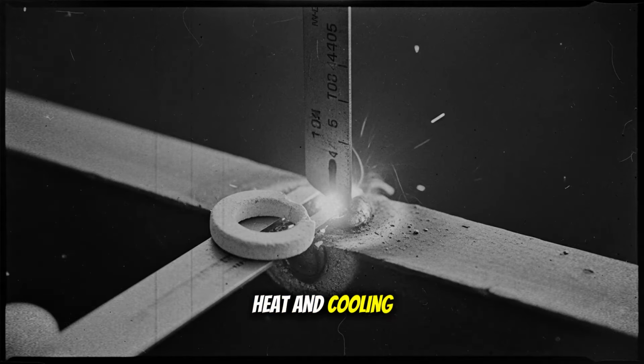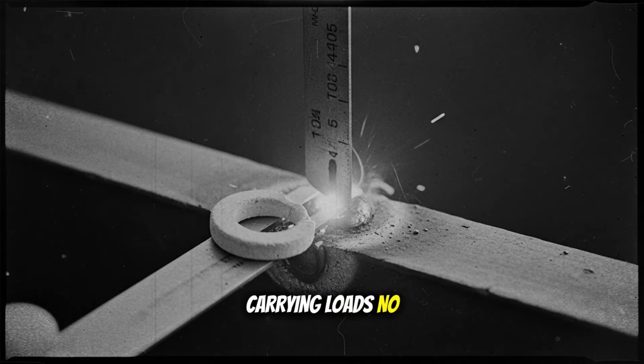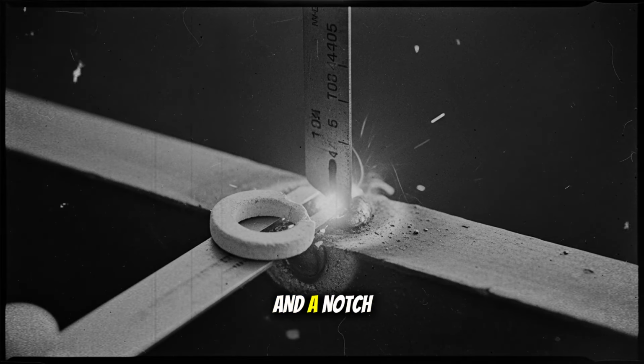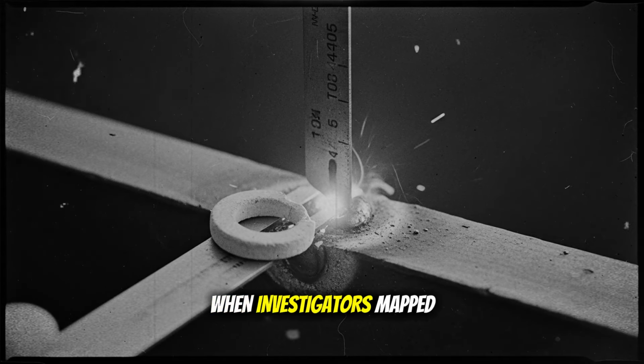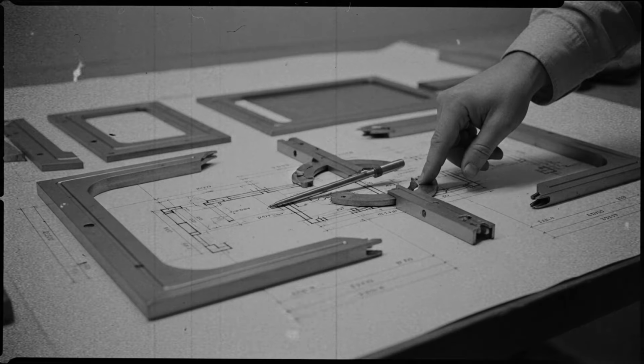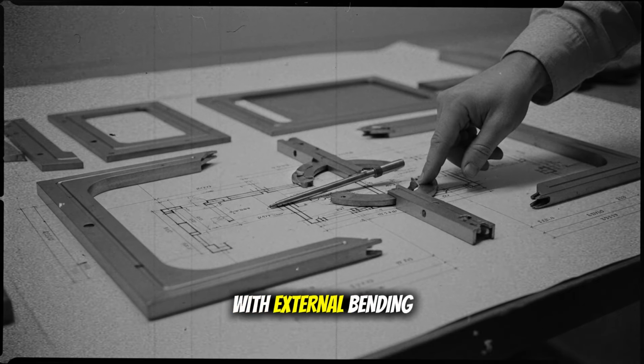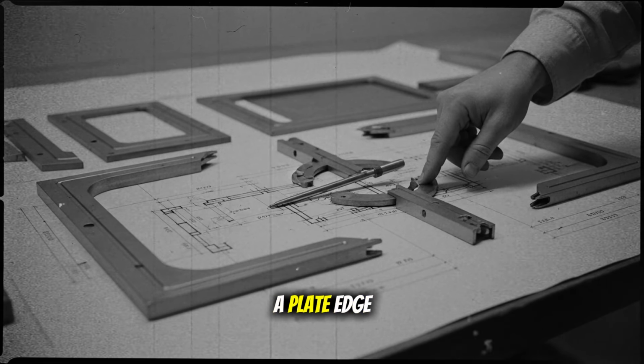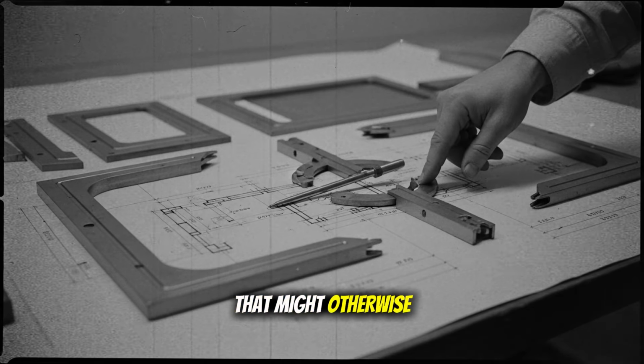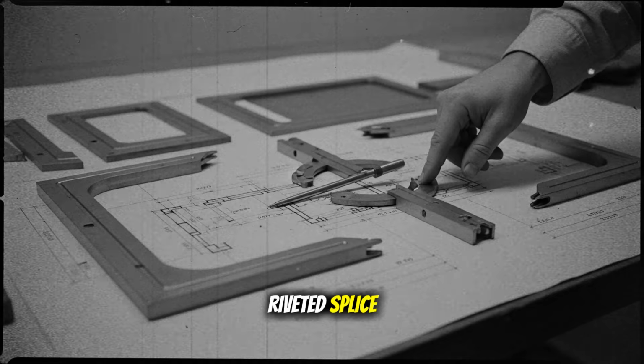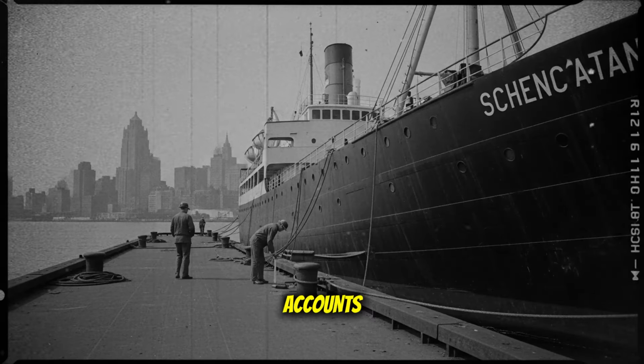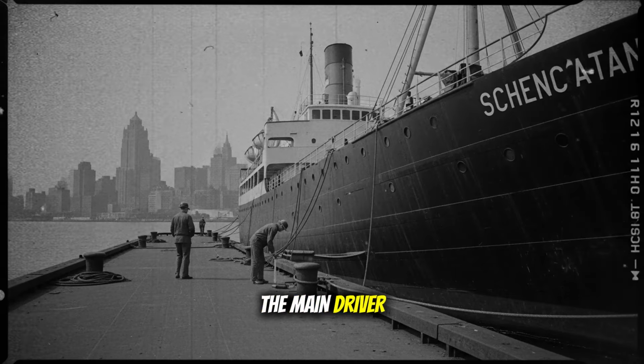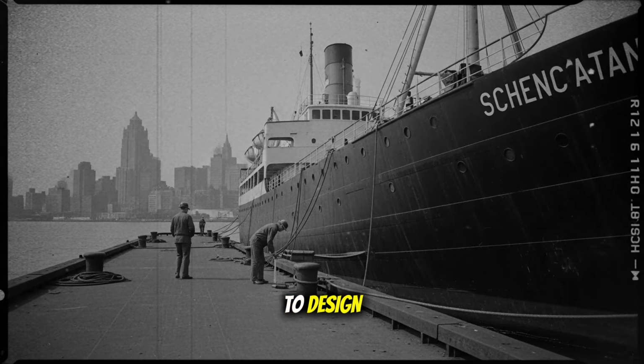Residual stress, the ghost written into the steel by welding heat and cooling, complicated everything, because a plate could be born already tense inside, carrying loads no gauge could see until the cold made them matter and a notch gave them a voice. When investigators mapped crack paths after failures, they often saw how internal tensions aligned with external bending to push a flaw across a seam and into a plate edge, accelerating a fracture that might otherwise have stalled in warmer water or at a riveted splice. In some Schenectady accounts, residual stress was singled out as the main driver, a reminder that sequence and heat history are not footnotes to design but part of the structure's fate.